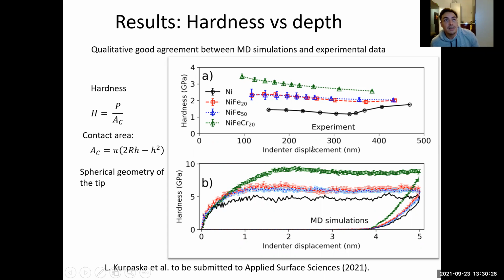Of course, this is the length scale for the experiments, and this is the length scale for the MD simulations. But you can see this bump here and this bump here, and then the decrease of the hardness as a function of the indenter displacement. And you can also see it here for nickel, iron, chromium. And for the other material, it is the same, this constant and this correspondence.